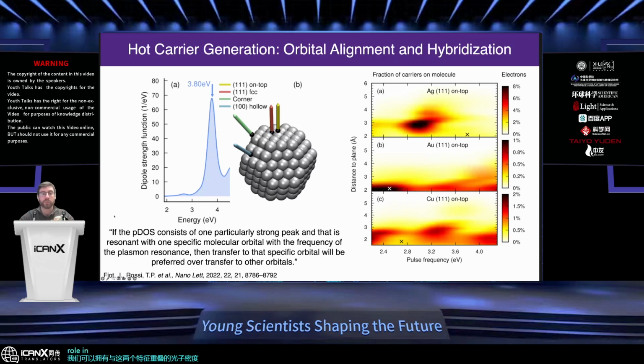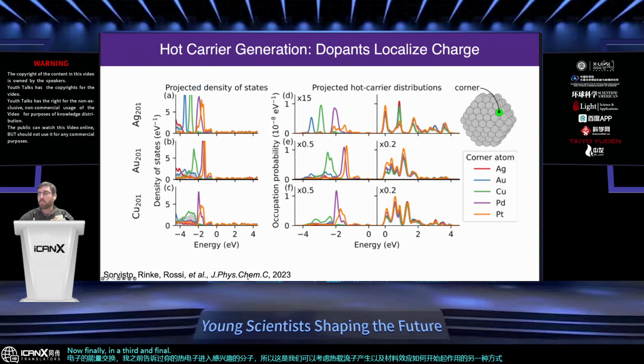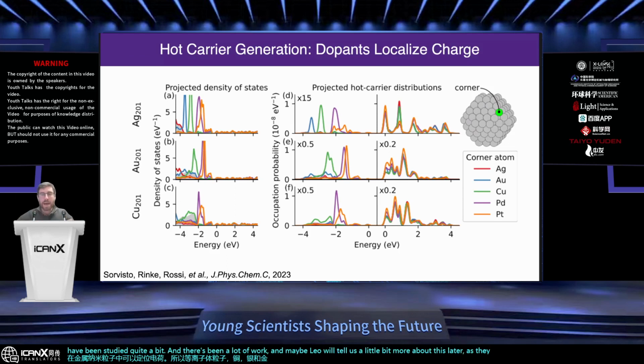And so that's another way we could think about hot carrier generation and how material effects are going to begin to matter through hybridization. Now, finally, in a third and final follow-up paper published in the Journal of Physical Chemistry C, again by Thomas Rossi and his coworkers in 2023, what they showed is that dopants in metal nanoparticles can localize charge. So plasmonic particles, copper, silver, and gold, have been studied quite a bit. And there's been a lot of work, and maybe Leo will tell us a little bit more about this later, is that you could put a platinum shell or a silver shell, and you can make these complicated nanostructured geometries with a lot of metal nanoparticles, but we don't necessarily have to have a shell or a large layer. You could actually put in a single atomic dopant into the nanoparticle itself, and that will change the projection of hot carriers, again, the electrons and the holes, that may localize in those defect sites on a surface.